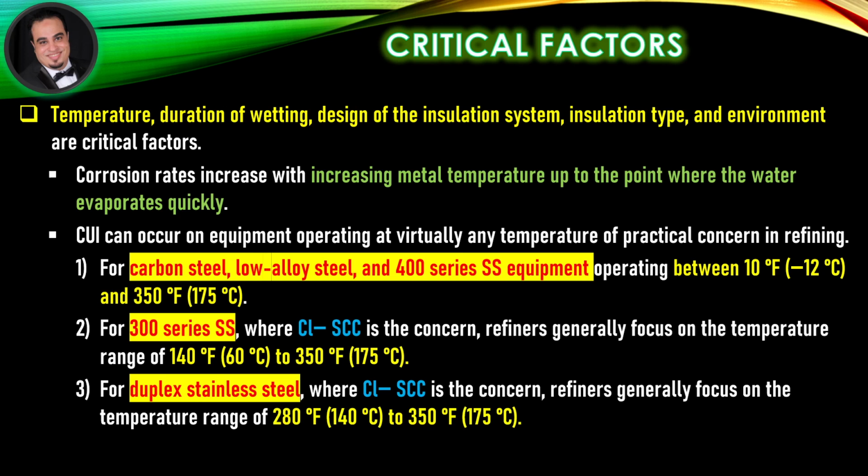For duplex stainless steel, where chloride stress corrosion cracking is the concern, refiners generally focus on the temperature range of 280 degrees Fahrenheit to 350 degrees Fahrenheit.